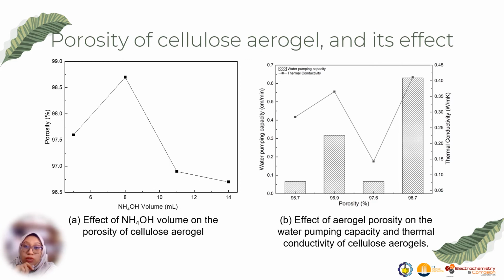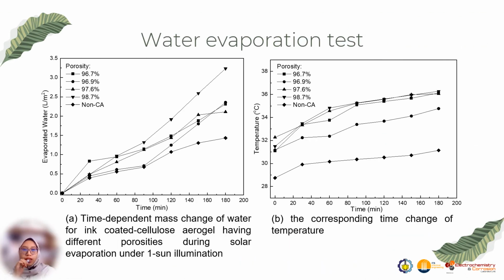The value of thermal conductivity for all cellulose aerogels with different porosity is still in the typical range of good insulating material. We also did evaporation tests with the aerogel material to compare cellulose aerogel ability as an SSG system. The evaporation rate of water under one sun illumination with the presence of uncoated cellulose aerogel was about 0.47 liter per square meter hour. It increased significantly when the self-floating coated cellulose aerogel was placed on the water surface and reached the highest evaporation rate of 1.062 liter per square meter hour.